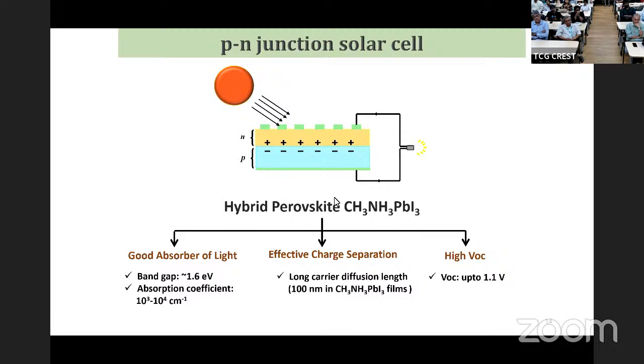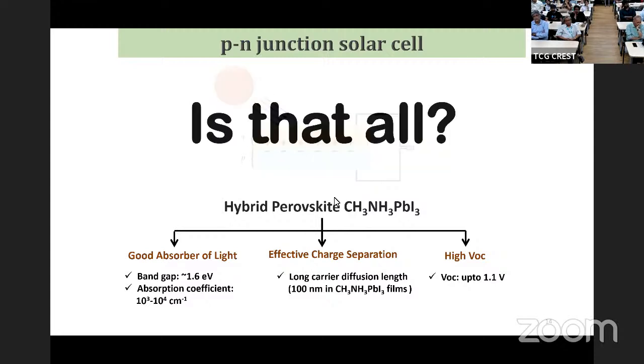And it turns out this material has nearly the ideal band gap, as I mentioned, 1.55 to 1.6 electron volt. It has an extraordinarily high absorption coefficient. It has long carrier diffusion length, so electron and hole can diffuse long distances, and the open circuit voltage is very large, up to 1.1 volts.